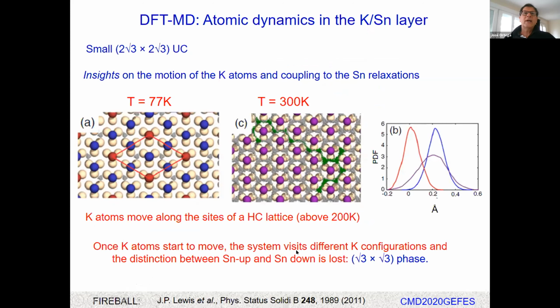So now let's see if we can get some insights into what the atomic mechanisms for this transition are, using DFT molecular dynamics. In this molecular dynamics, we have to use a small unit cell, but the idea is to get a good insight on the motion of the potassium atoms and how this motion on the surface is coupled to the tin relaxation, the tin up and down relaxation.